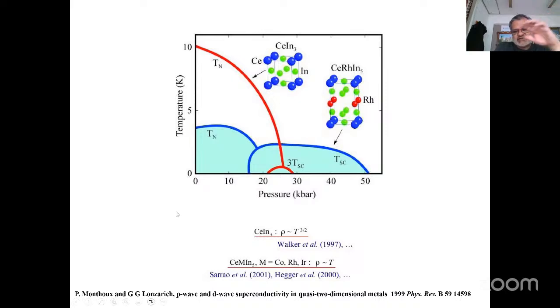And this dimensionality, still in a solid system, definitely was very intriguing. It, of course, harks back to high TC superconductors and their anisotropy and why they have such high TC. Here, although TCs may be much lower, phenomenologically speaking, we go from 120 millikelvin to about low kelvins. So there's a decade of change in TC by change in dimensionality in this kind of system.